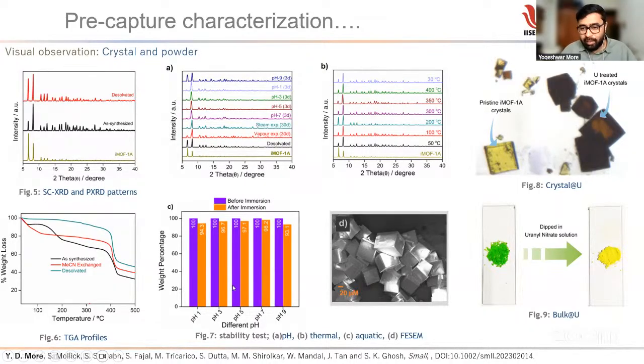And this is what our working range is. So before going further, we did a visual observation. We had the uranium solution, and in this uranium solution we put the MOF and we saw an immediate color change. This is the MOF crystal in pristine form, without any uranium, and this is the crystal which was dipped in uranium and taken out.